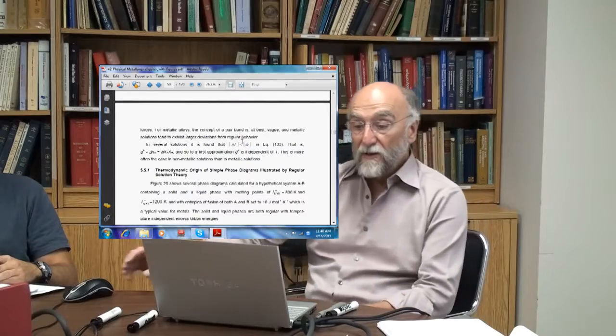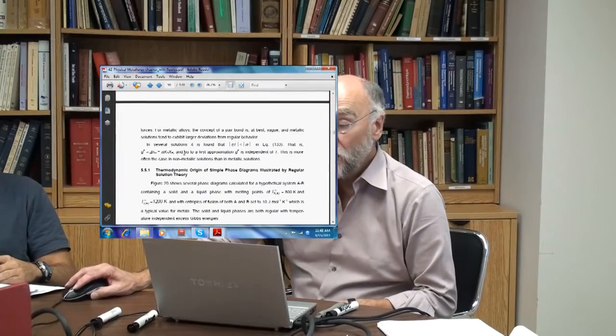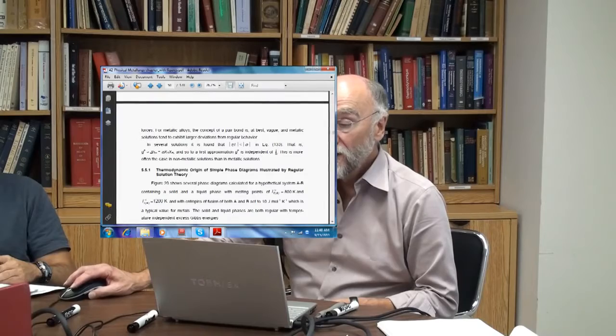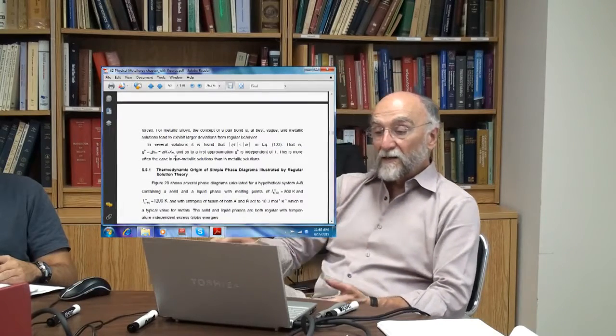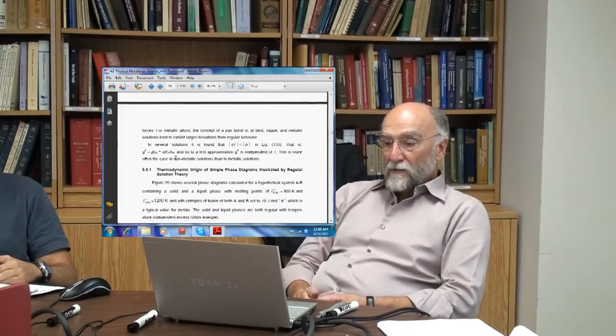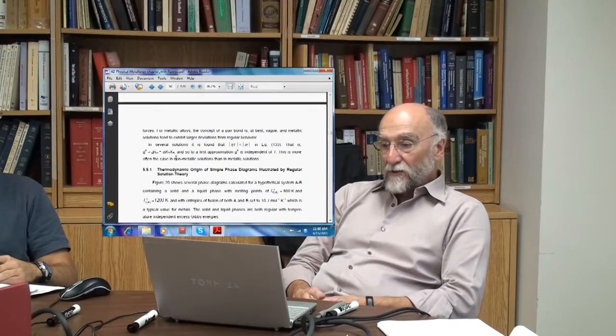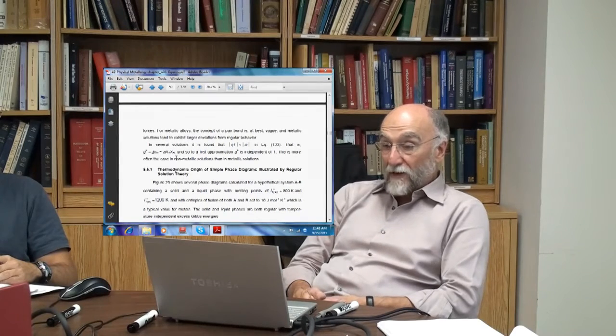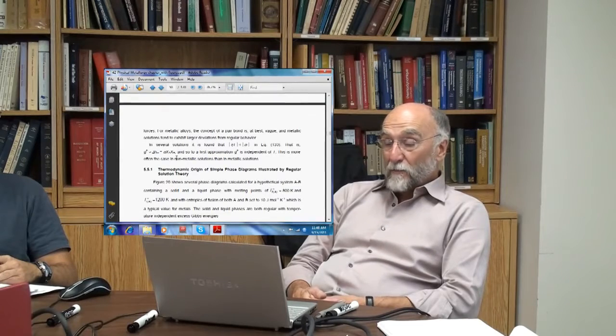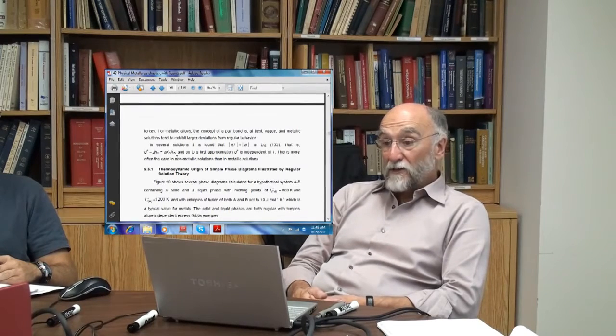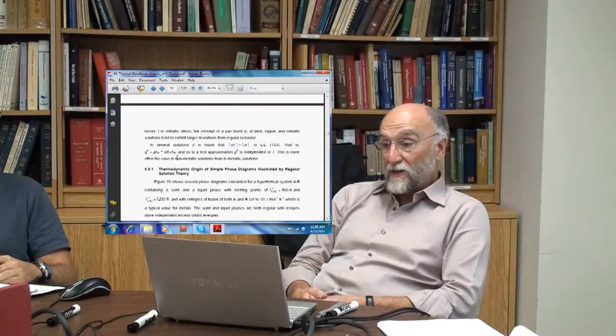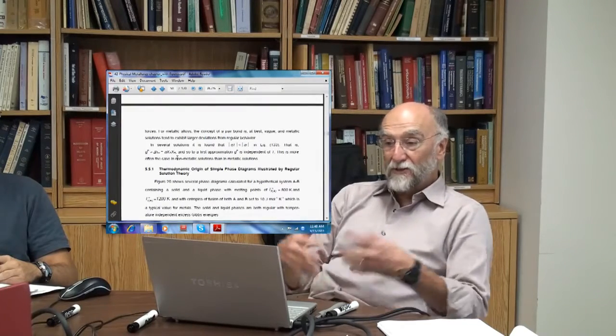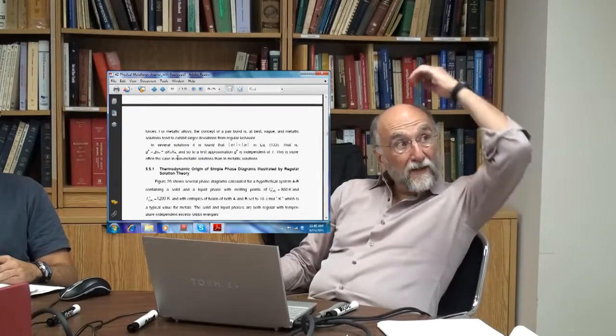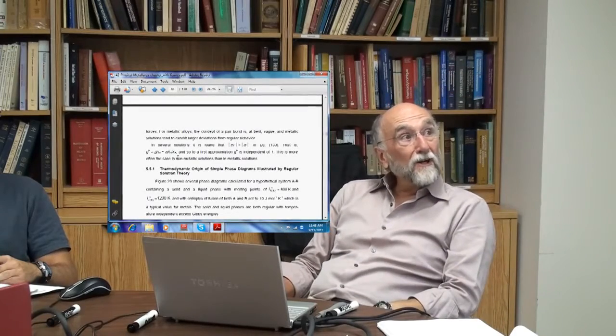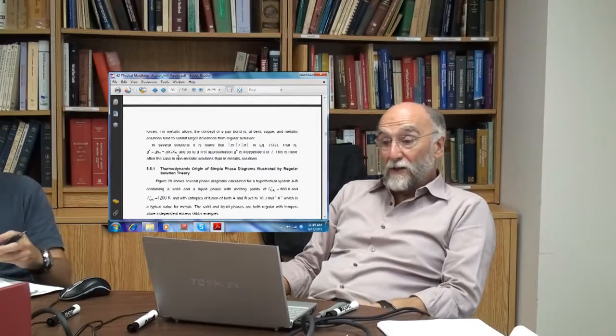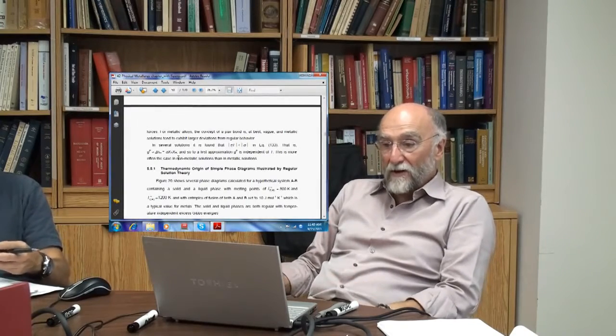Okay, so G^XS is omega X_A X_B. So to a first approximation, G^XS is independent of temperature. Again, this is more often the case in non-metallic than in metallic solutions. So even if you find a G^XS that's fairly large in a molten salt or a molecular solution, you'll often find that the S^XS is quite small. But in metallic solutions, you can sometimes find that the delta H term is not that big, but the T·S^XS term can also be quite large. So metallic solutions tend to have less of a tendency to be regular, or at least not strictly regular for sure. And I think it's basically because the idea of a pair bond is kind of vague.